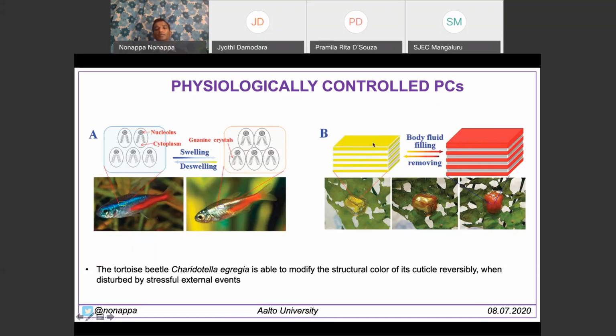Now, guanine has a 1.83 refractive index, whereas cytoplasm is close to water, around 1.4. And so with this alternating layer, when, for example, this beetle is attacked by a predator, you touch it, you will see the color change immediately to red within a few seconds. This is because it is able to excrete some body fluid that will fill this cavity or change the refractive index, that eventually changes the color of this object. This is a dynamic and physiologically controlled color.